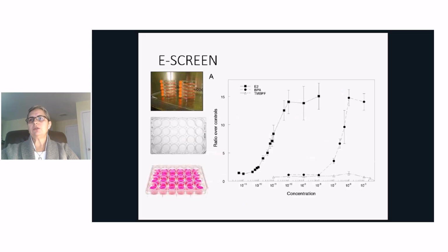So these are typical dose-response curves. We use estradiol as a positive control, so this is your typical estradiol dose-response curve. We use bisphenol A also, as a chemical with estrogenic activity. These dark dots are the BPA dose-response curve. And here at the bottom, this flat line is tetramethyl bisphenol F. So in the presence of TMBPF, the MCF7 cells that need estrogen to proliferate did not proliferate, which we concluded means that TMBPF does not have estrogenic activity, at least in this particular assay.